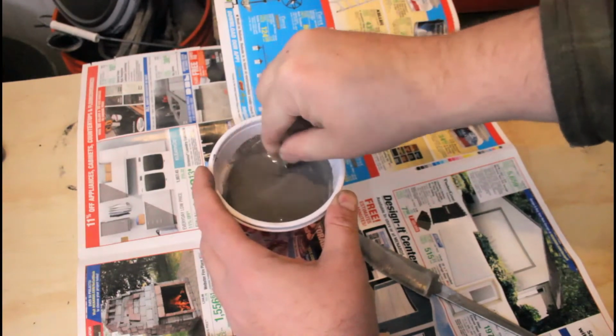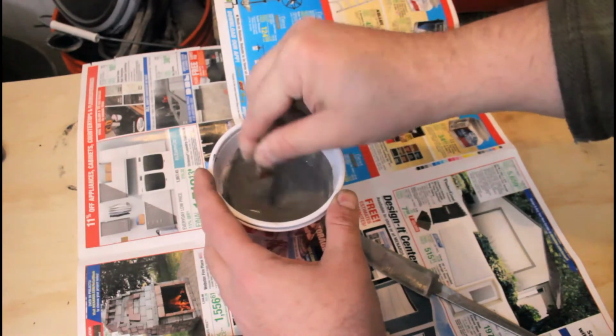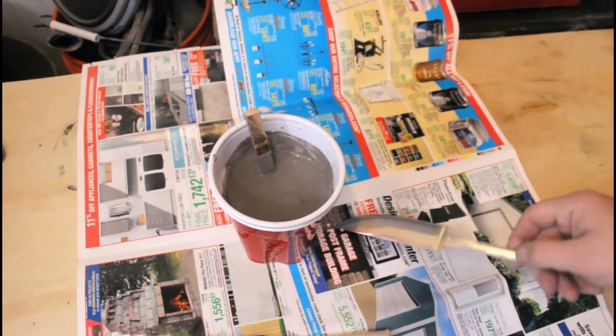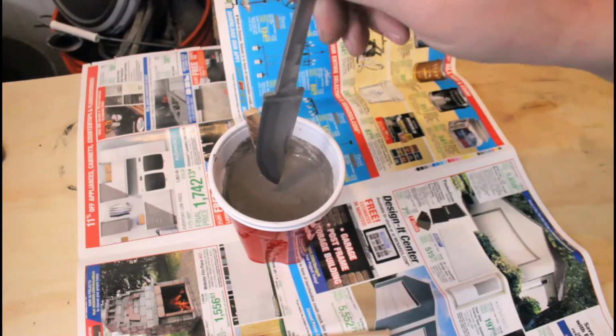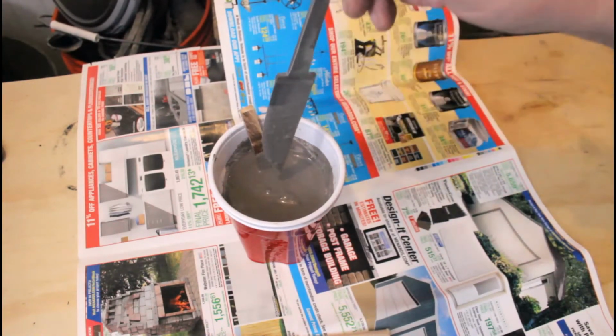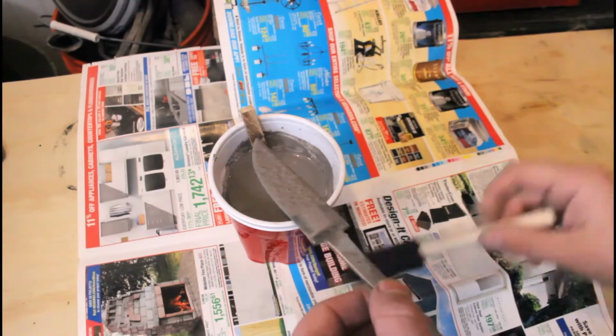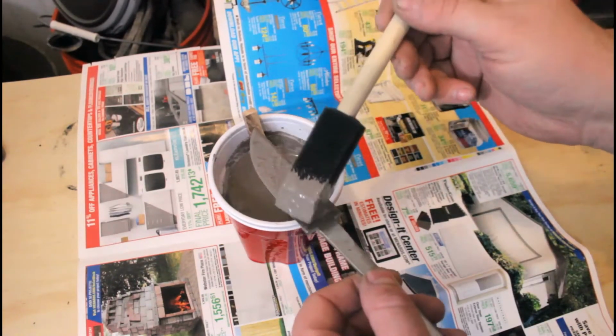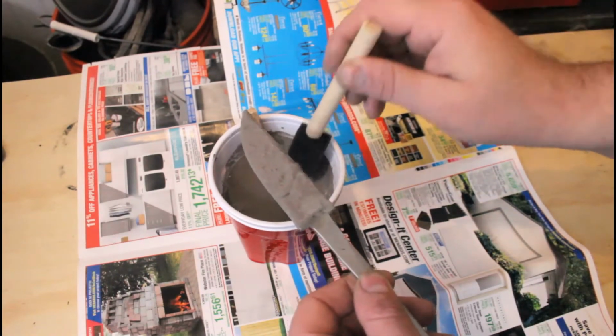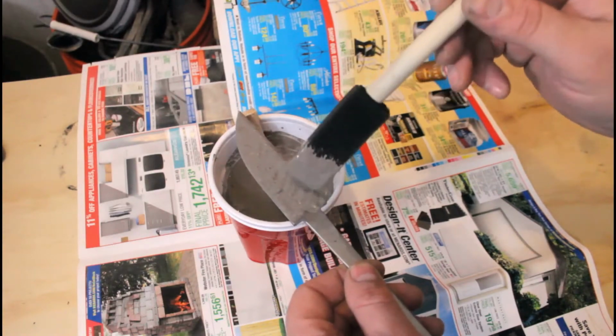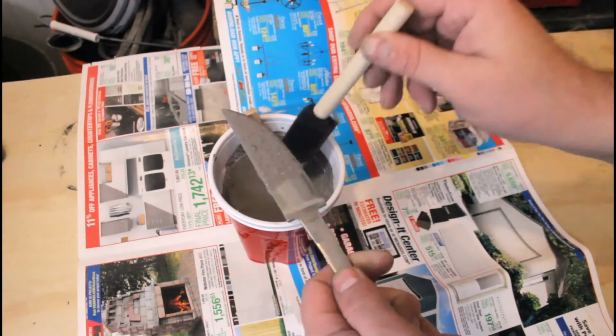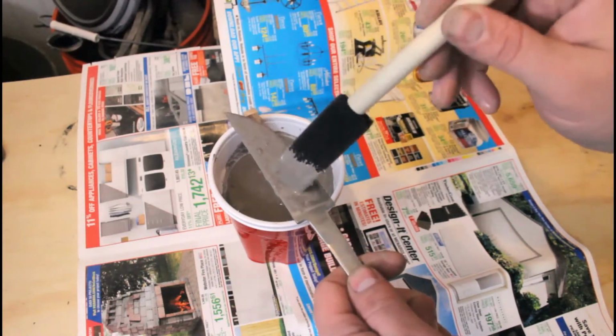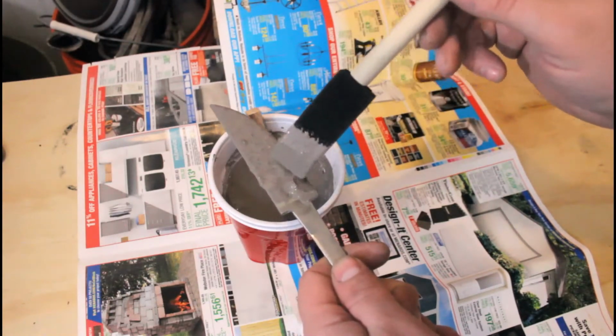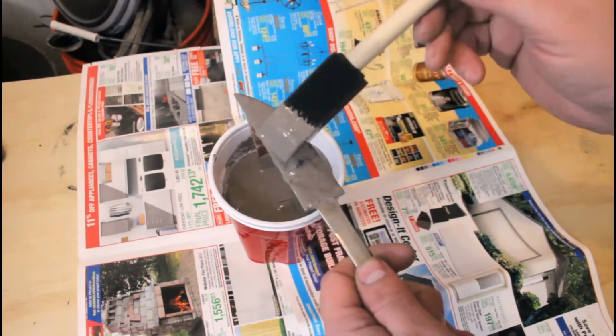You're supposed to heat treat blades like this wrapped in a pouch made out of stainless steel foil to prevent decarb and forge scale and all sorts of things from building up on the surface of the blade. But I don't have any stainless steel foil, so instead I'm going to try to coat the blade with a thin layer of goop made out of water, wood ash, and furnace cement.